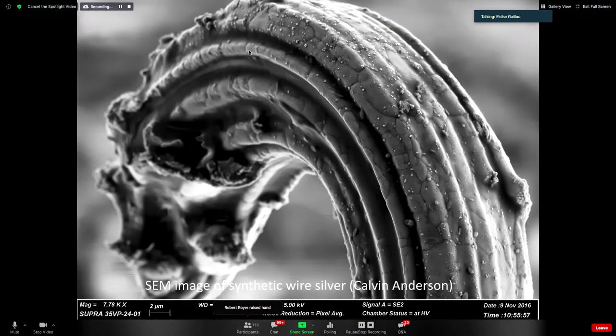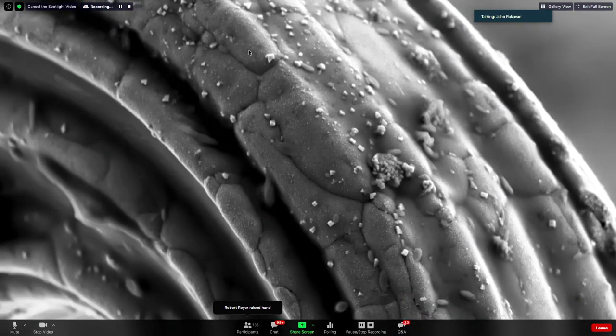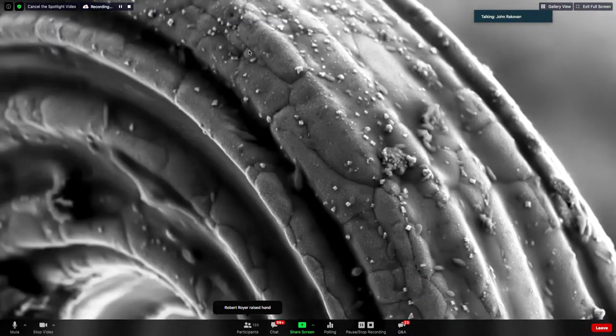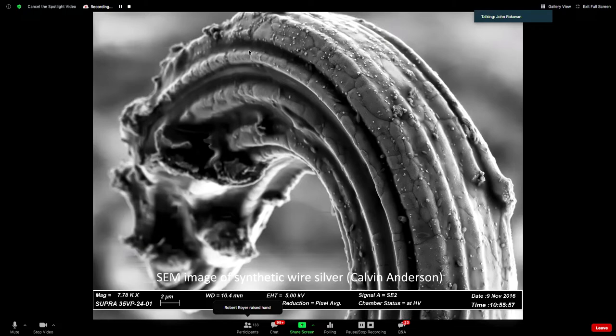Okay. And the people were seeing the bright spots on the wire crystals. I guess that's just dust, right? Is it really the silver, or did you have some little specks on the SEM? Could be. Actually, if you can zoom out, Brian, what I want to find here is, okay, so I'm looking at the data. That's a secondary electron image, which means that the brightness is not a function of mean atomic weight. So that's just a surface feature. I think it's dust.